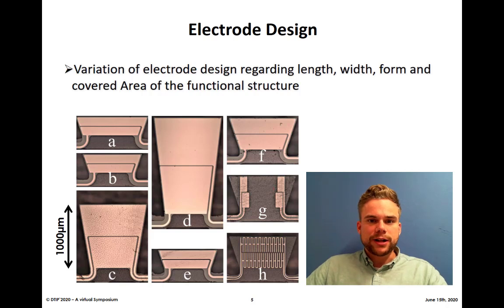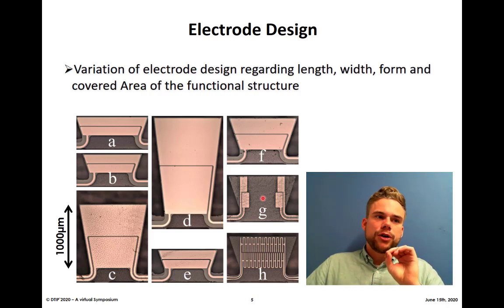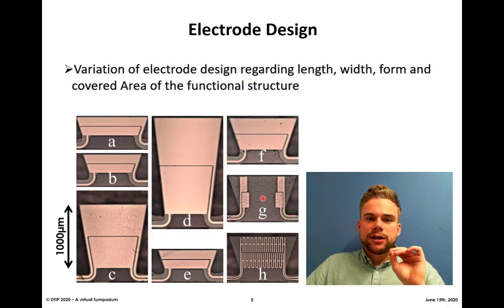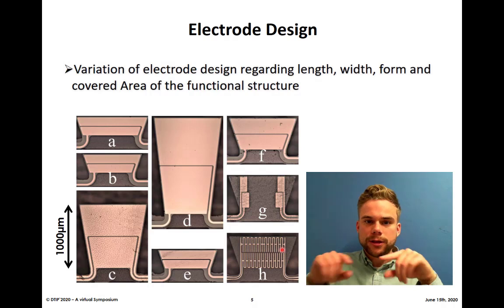And then we have a different set of electrode designs for G and H that vary completely from the other forms, because in that case we don't have a totally covered area for the electrodes, but a very specific other design. For instance, with G we have segmented electrodes. We changed the form in a way that we decoupled the left and the right side of the flapper. And what is also very important here, the aluminum nitride layer is only under the electrodes for the flapper G and H. So we have a very high decrease in the covered area of aluminum nitride, which is, as we know, a rather stiff material. So this was also to see how we can reduce the stress inside the layers of the flapper. So this is what we did with G and H, a meandering structure for the electrodes, and also underneath the electrodes a meandering structure of the aluminum nitride to decrease the stress inside the layers.